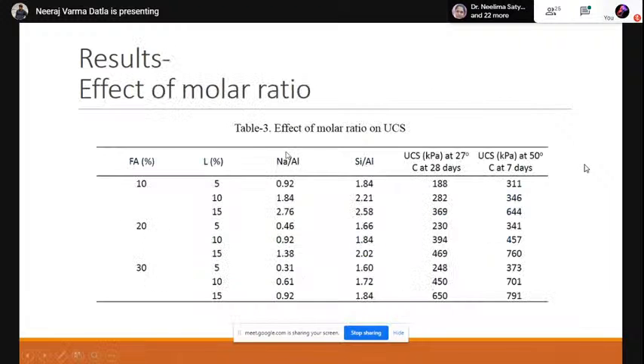And now, with respect to the effect of molar ratios, for the same fly ash content, with increase in the liquid activator, the sodium by alumina ratio is going to increase. But with increase in the fly ash content for the same liquid ratio, it is going to reduce because the alumina content increases. So the ratio is going to get reduced.